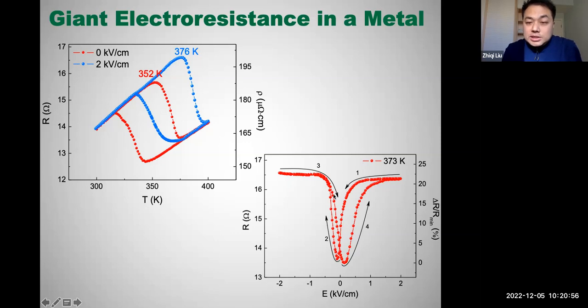Therefore, the resistivity of this material is varied. For example, it has a 21% resistance change at around 100 Celsius degree. So this is really a remarkable value for a metal material, because metals exhibit a large number of free carriers. If you try to dope electrons or holes into these materials, you could hardly change their resistivity. But by virtue of this kind of metal magnetic transition, a small piezoelectric strain can change the resistivity significantly.